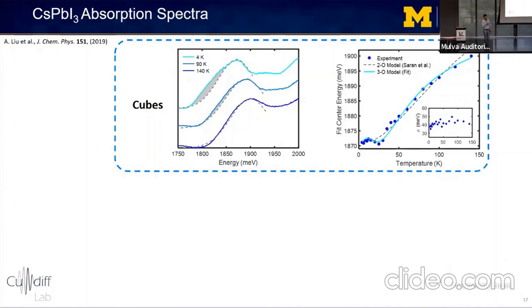And the temperature trend has this funny curvy shape because excitons in these nanocubes couple not only to acoustic phonon modes, but also multiple optical phonon modes of the cesium lead iodide lattice. The peak width, on the other hand, doesn't change very much with temperature, which suggests that the peak width is simply the inhomogeneous line width of the ensemble.